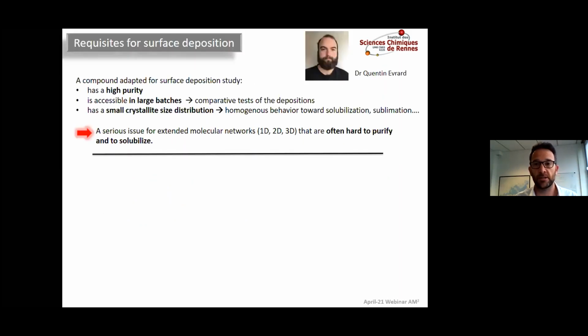So why are we doing this? It is because this is work that was driven by Quentin Evrard. A compound adapted for surface deposition is quite different from the ones that we use in a traditional SQUID. We are not picking a crystal in the middle of a mother solution and trying to put it in a SQUID and so on. We need powders with high purity, accessible in large batches to be able to perform comparative tests of deposition. Because when you do 20, 30, 80 tests of deposition, you have to be sure to start from the very same material.